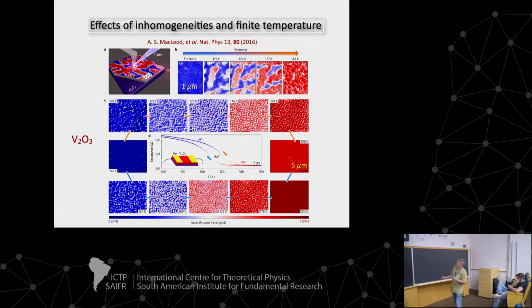This is for V2O3, the kind of system that I showed before. Same kind of data, and you have the same kind of patches of different phases coexisting with each other. Okay? So you see very clearly here these patches. And I call your attention to the sizes here. So this is very large. These are very large domains coexisting with each other. This is micrometer sized. This is not microscopic. This is very large.